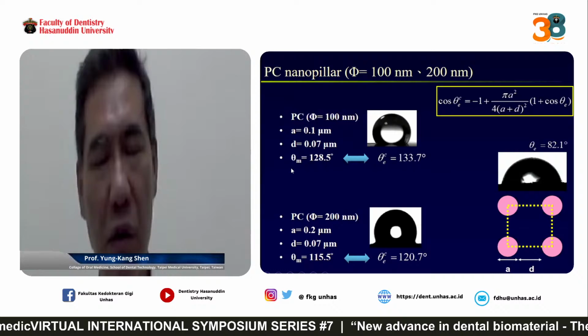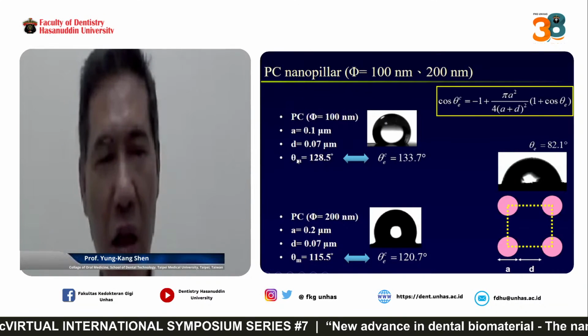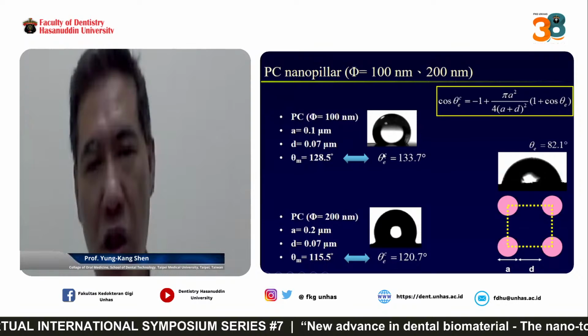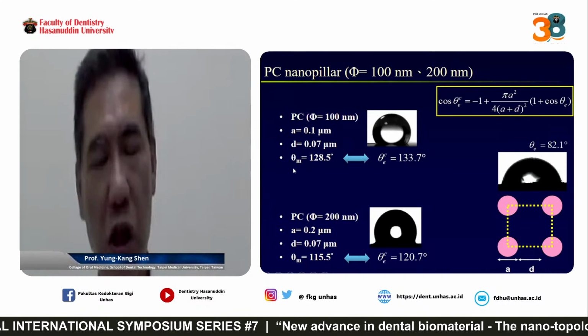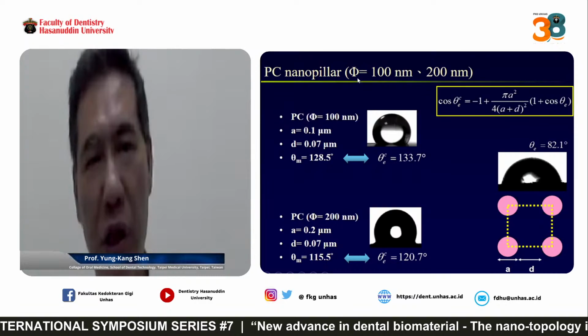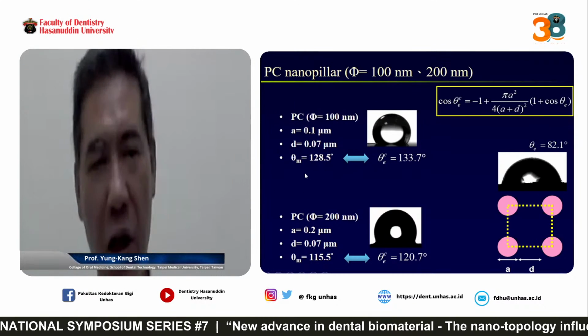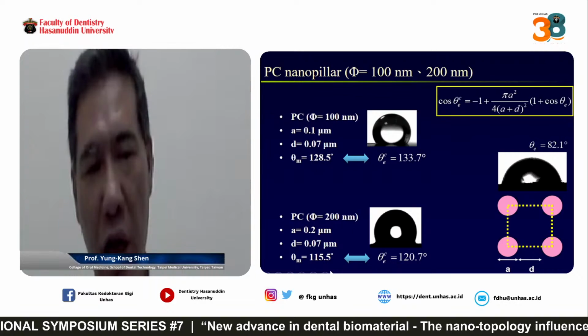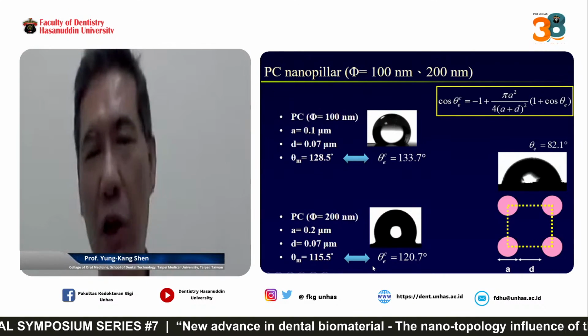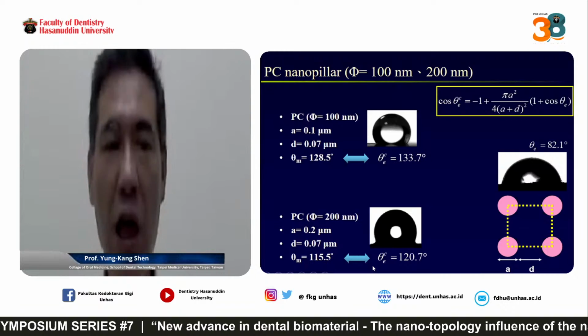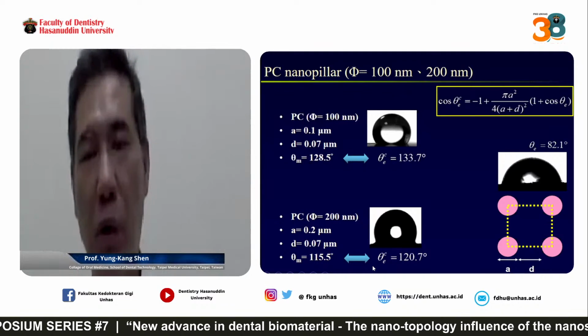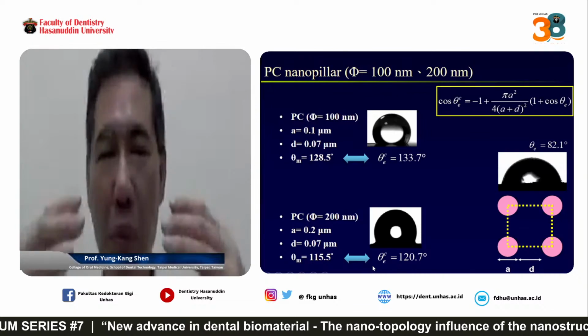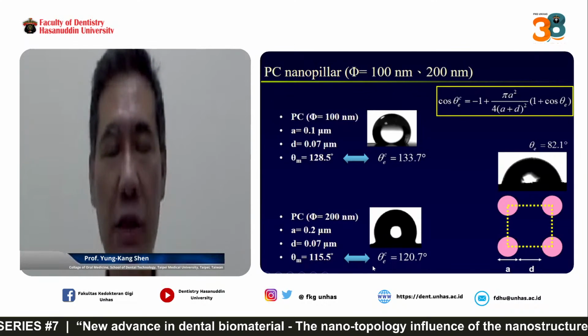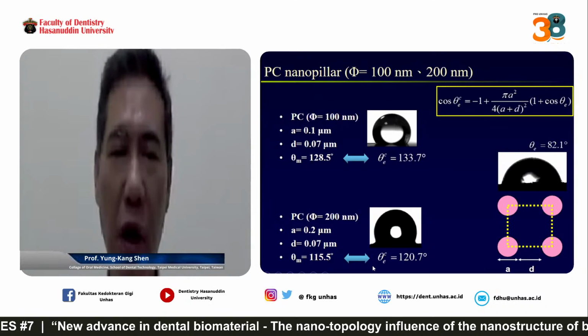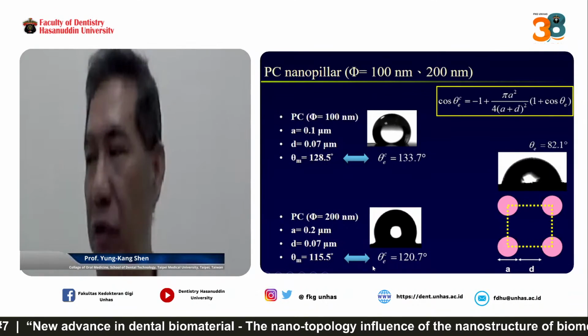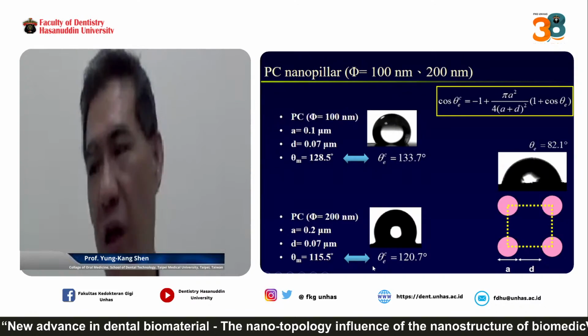So this is also for the experiment and the theory. Theta M is the experiment, theta CE is the theory. In our experiment, we can get the PC nanostructures, 100 nanometers and 200 nanometers. This is the experiment, this is the theory, and you can see the theory and experiment contact angles are very close. So we can double check: we do the experiment and use the other professor's published research result, and we get a very similar contact angle. Sometimes when I do an experiment, I am afraid my result may be good or false. We can use the theory to double check this result.